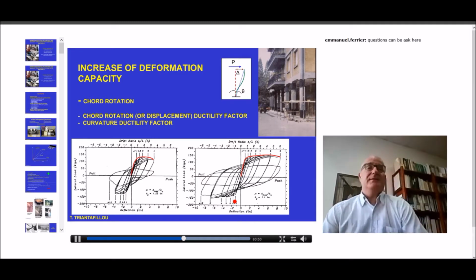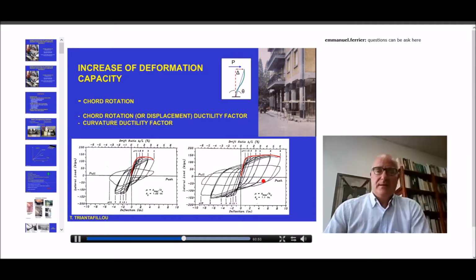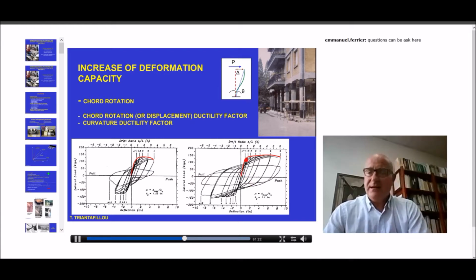I talked about increase of deformation capacity. This is what I refer to. This is the response of a typical column before retrofitting with FRPs. We reach a ductility factor that is relatively low, let's say 2, 3 maybe, and by locally confining the column, that is by locally applying the fibers at the ends of the column, we increase the ultimate strain of concrete so that the member can deform more. In that case, ductility goes up, but this is not the case for strength, and we should try to remember this. This is a very important point.